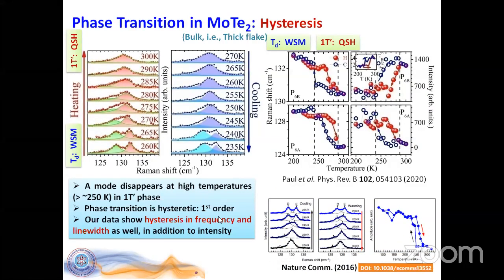Now, of course, ours is not the first report of hysteresis in intensity. This article in Nature Communications, way back in 2016, showed that there is a hysteresis of this mode, and here is the intensity that shows the hysteretic behavior. We added the interesting observation of hysteresis in frequency as well as the line width, as we can see in this inset.